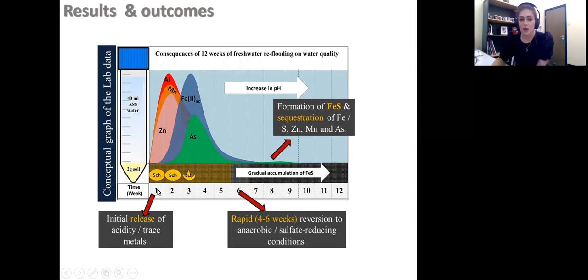So at this stage, somewhere between 1 to 4 weeks following the freshwater reflooding, we observed the gradual depletion of schwertmannite in our sample, and an initial increase of iron 2 concentration and arsenic, and then a gradual decrease, and finally somewhere between 4 to 6 weeks following the freshwater reflooding, the aqueous phase was depleted of trace metals and metalloids, aluminium, iron 2 and arsenic. The formation of iron sulfide minerals had a visual indicator, the black color, transformed from the orangish brown color of the initial iron 3 containing mineral, which was a good indicator that we have the formation of iron sulfide minerals in our sample.